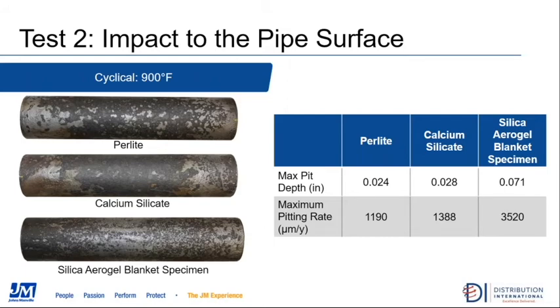When we look at the results of the second test, again, to review, we did the perlite, the calcium silicate, and the Silica aerogel, and we can see those pipes there on the left. We cycled this test between ambient and 900 degrees. And then we can see in the graphic there to the right, that table, we can see the results. We can see the perlite and the calcium silicate. Those pits extended about the same into the pipe samples. And then again, we can see that the pits extended further into the Silica aerogel sample.